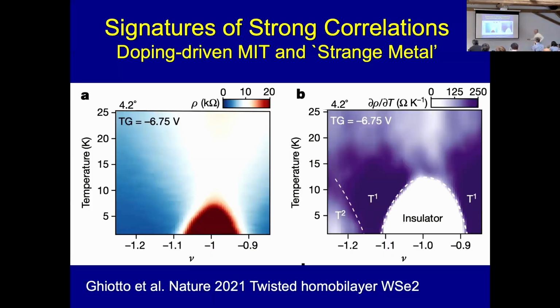This is one, for example, from the Columbia group, the twisted homobilayer tungsten diselenide, where as a function of temperature and filling, which again can be gate controlled, there is a transition between a low resistivity metallic state and a high resistivity insulating state. And even more beautifully, in this regime close to the insulator, it was observed that transport is T-linear, and you may want to call this a strange metal, like in cuprates, where farther away from the insulator, you get something like a T-squared behavior.